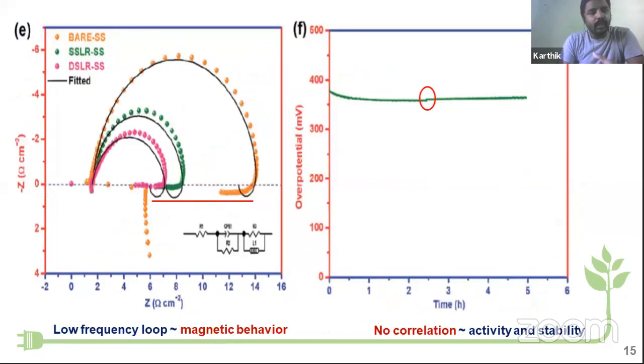Figure E shows the electrochemical impedance spectroscopy of the as fabricated electrodes. It is clearly seen that the Nyquist loop or semicircle is high for the bare stainless steel, whereas for single side it is reducing, and for double side it is further reducing. Once the semicircle is reducing, it implies that the charge transfer resistance is reducing, and simultaneously the conductivity is increasing. In addition, all three Nyquist plots show an inductive loop at low frequency, highlighted by a red line, which arises due to the magnetic behavior of the materials. The bare stainless steel also has magnetic behavior, but after laser radiation, its magnetic behavior is enhanced.